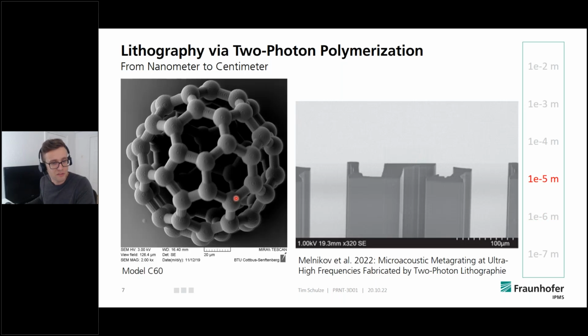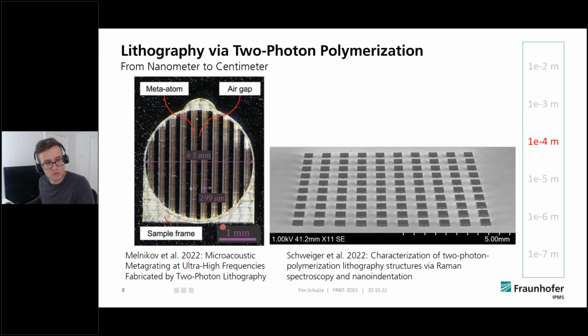Here is just a little test of the so-called C60 molecule, also called the buckyball. And also colleagues of mine use this for acoustic metagratings. So the idea was to use the metagratings to shape the wavefront coming from ultrasonic transducers. And this has also been published, and according to my colleagues, they were quite satisfied with the results. And here in a higher scale, you can also see this metagrating that has been designed. So this was just put in front of one of our ultrasonic transducers, and by this we were able to shape the wavefront of our substrate.